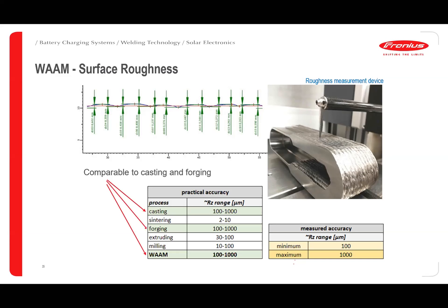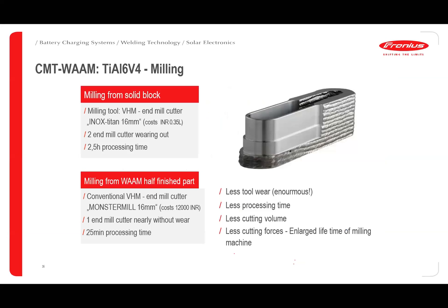Okay, moving on to the next slide, you will be able to see where we have done a milling. You can see as if it is milled from an original solid block. There was absolutely no defect. And when we do this size of component from a solid block, we have to use close to 2 milling cutters, and we have used around 2.5 hours of processing time. But when we use WAAM, a process like layer manufacturing, we were able to use only one end mill cutter, and we were able to process this particular component in just 25 minutes.